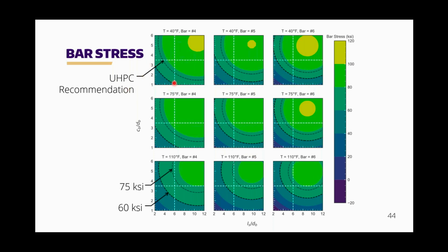What I'm also showing in each of these plots is some white lines, which would tell you the UHPC recommendation. They would recommend a cover, CB, in this case, greater than 3.5, and a splice length greater than 6. And so what we're really looking at in each of these plots is what's going on here in the red box. We're also showing contours called out for both 60 and 75 KSI, so you can see it.